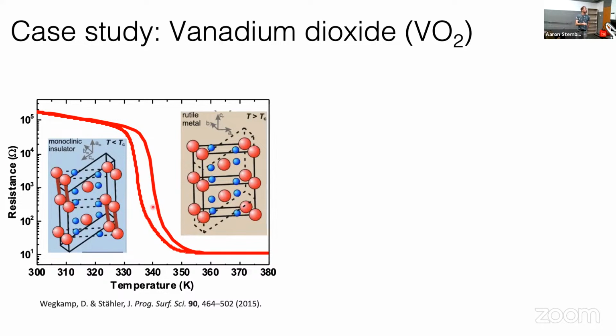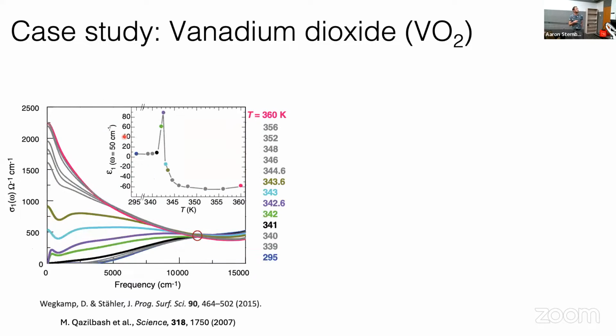One of the features, however, that you can see in this measurement of resistance is that the resistivity changes in a way that appears to be continuous rather than abrupt, which is surprising for a first order transition. And so in this talk, we're not even going to get to the electronic versus structural transition. We're really just going to be focusing on the electronic transition, the role of nucleation and growth, which is still something that we're just learning how to address.